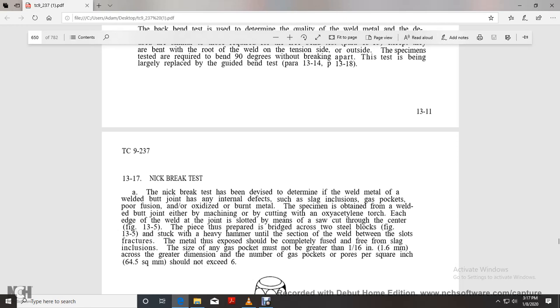The weld should be completely fused and free of slag inclusions. The size of any gas pocket must not be greater than 1/16 of an inch. If gas pockets are present, the number of pockets per square inch should not exceed 6.